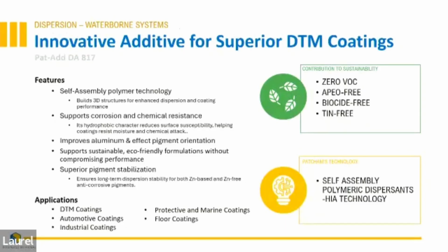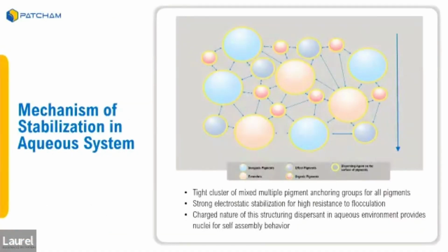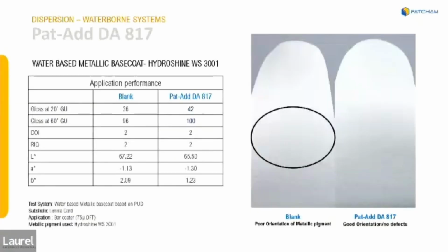The dispersants that I just previously described for solvent-borne systems are also available for waterborne systems. The properties that it provides are pigment dispersion, resistance to flocculation, and self-assembling properties so that the dispersant itself will participate in the long-term storage stability of your pigment dispersion to prevent materials from separating. The mechanism in aqueous systems is the use of other ions and materials and itself, its ability to associate with them in combination with and during the pigment stabilization stage, during long-term storage.